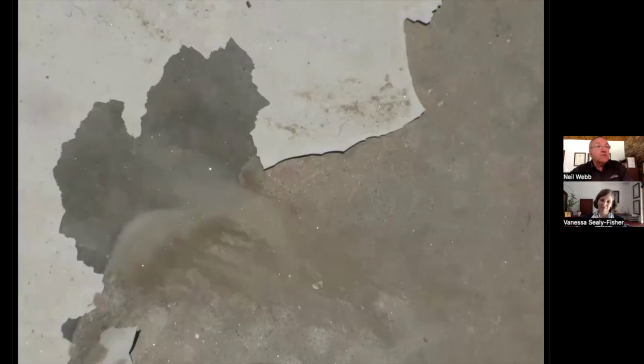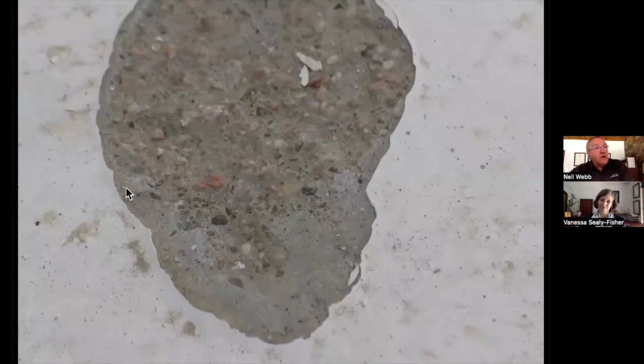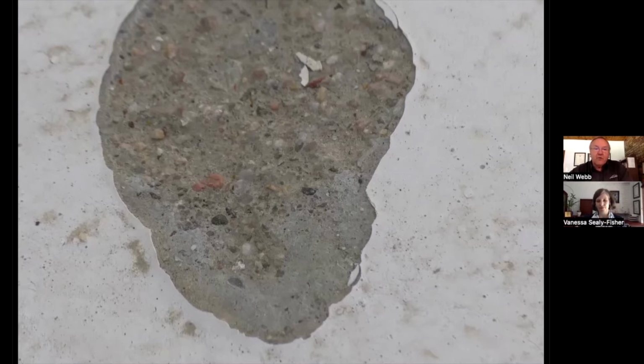Looking more closely at this situation, there's a thin layer of what we call laitance on the surface of the concrete, as indicated by the cursor. And that laitance is a cement-rich layer. It's very weak, it's very porous, and you have to get rid of that if you want even your epoxy penetrating primers to stick, because without removing that, again, you just land up with mass delamination. That's the surface that you want to coat. And as you can see, it's fairly rough.